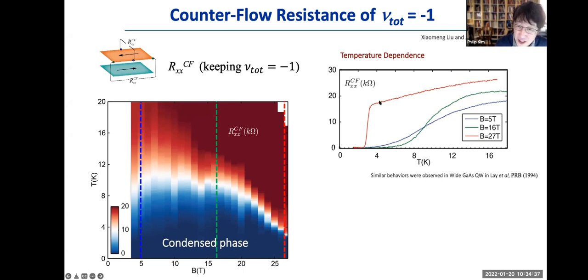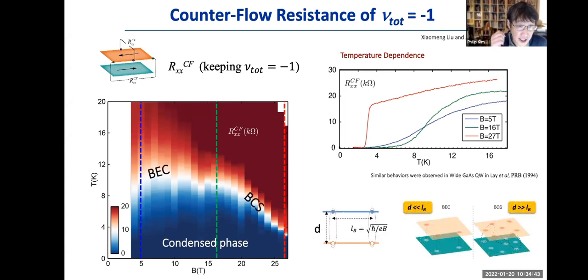Indeed, the transition happens sharply, like a superconducting transition. This is what theory expects to see in this type of BEC-BCS crossover in the system. So this gives you another example that by just combining van der Waals systems, one can realize a macroscopic quantum state, which can be rather robust. And that brings up interesting physics.